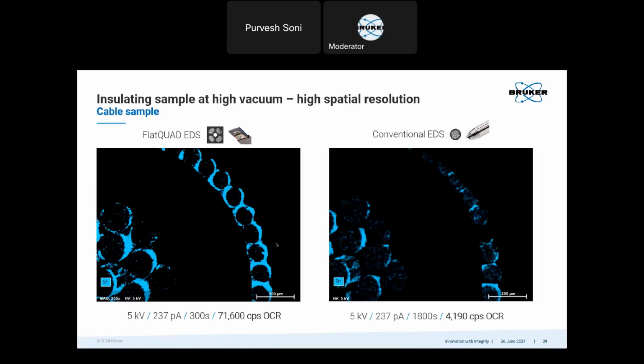So yeah, this is what you gain when you have a four-segment detector and you are measuring very close to the sample. That data loss is very low because of shadowing or topography. And also because of the high count rate for this measurement, I only had to measure for 5 minutes, but because of the low count rate of a conventional detector, I had to measure for 30 minutes.